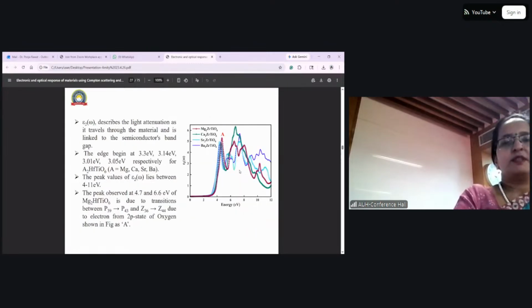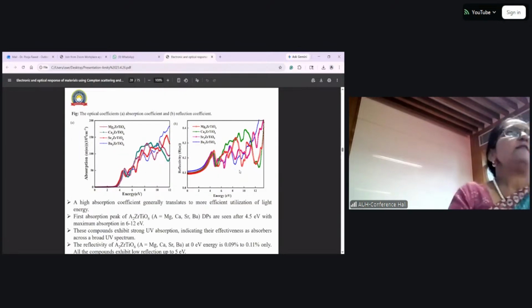Similarly, here it shows the imaginary component of epsilon. It shows how the light will be attenuated when it is traveling through the material. Then if I am incidenting light on a material, it can be absorbed, it can be reflected, it can be transmitted. So we checked whether it is absorbed or not. Unless the light is absorbed by the material, it cannot go for any practical application. So we found that these compounds show good absorption in the UV range, that is greater than 3 eV or 4 eV. So these compounds can be used for UV sensors, UV detectors, etc.